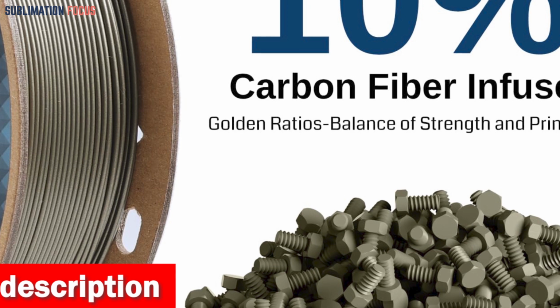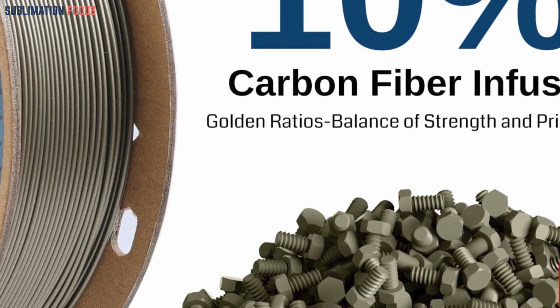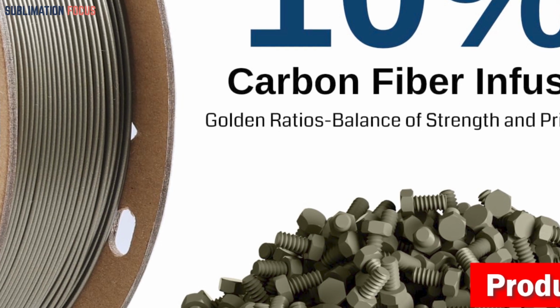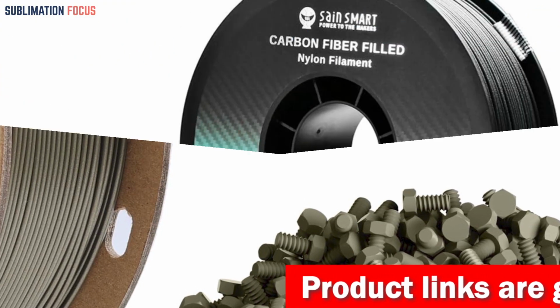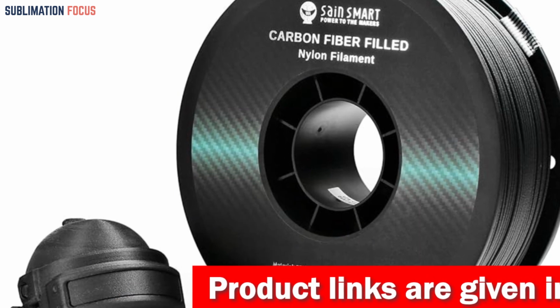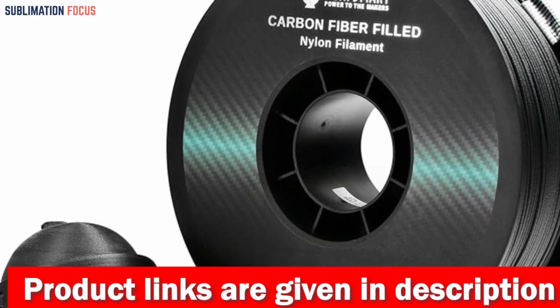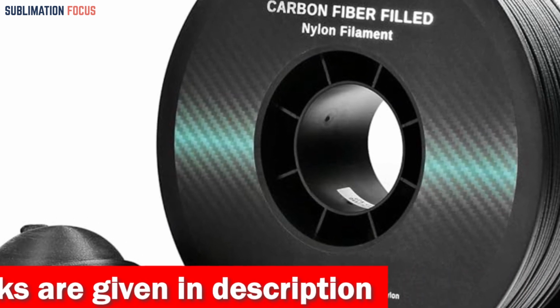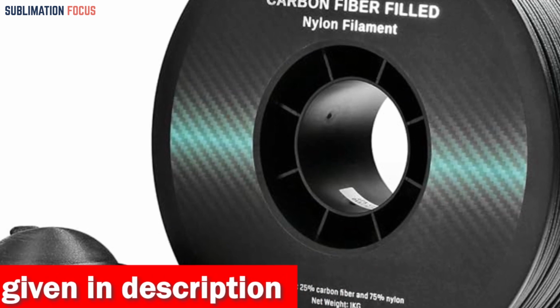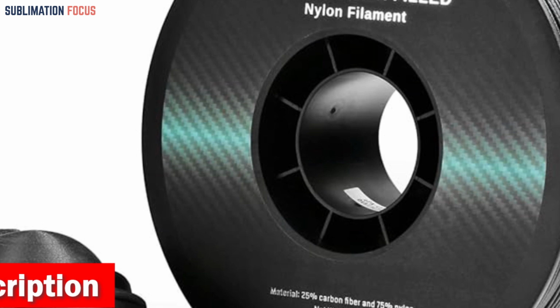Further, a minimal fan speed of 0% and a print speed ranging from 40-60 mm/s are essential components for attaining exceptional outcomes. To unlock the full potential of your 3D printer, it is recommended to equip it with a durable, abrasion-resistant steel nozzle, preferably with a diameter of 0.6 mm or larger. This will help prevent nozzle clogs and ensure smooth printing. It is crucial to perform regular maintenance on the nozzle to maintain optimal performance.